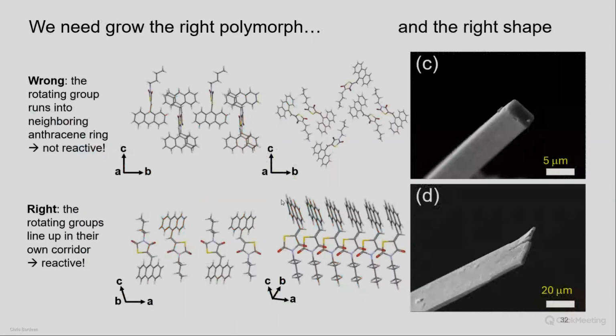And the one caveat here is that you do see polymorphism for many of these molecules. I sort of skipped over that. And so one key is to grow the right polymorph. This is the wrong polymorph, where the isomerizing tail is going to bump into the neighboring anthracenes. The right polymorph is one where you basically get this head-to-head stacking, and all the isomerizing tails are lined up, so they give each other room to move. When one moves, that gives room for the others to move.